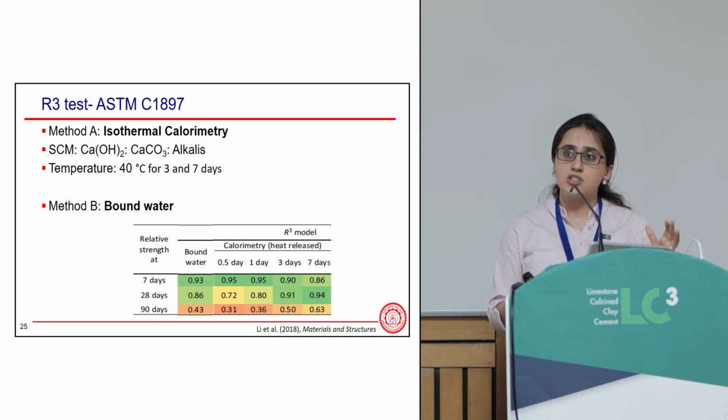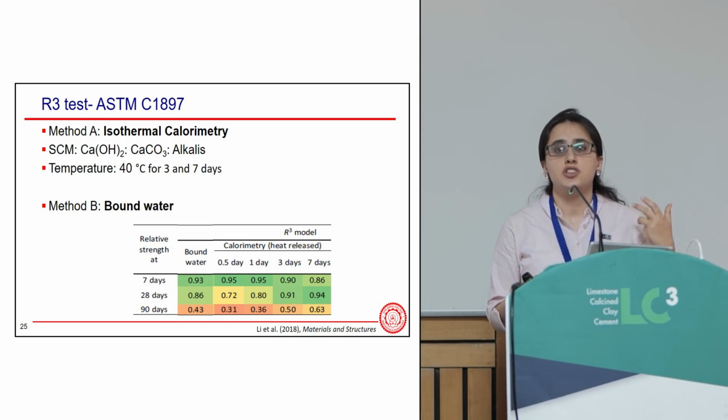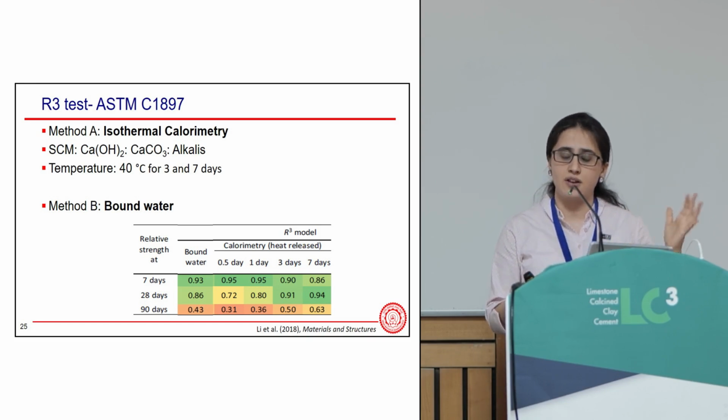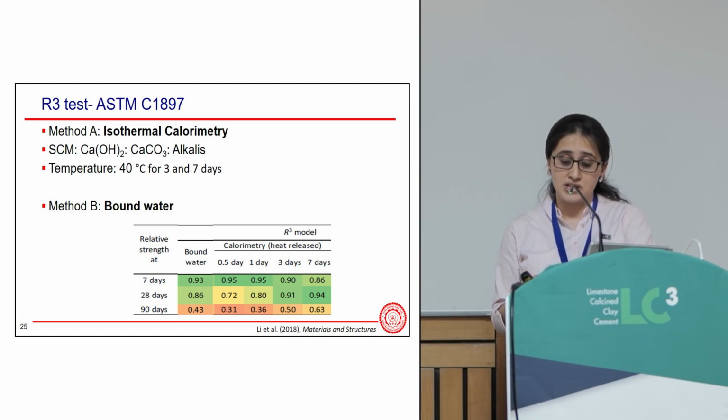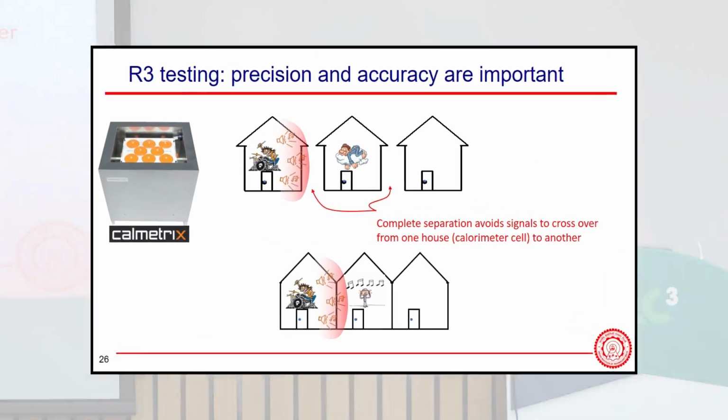There have been a lot of studies done on the R3 test using different types of SCMs and different types of clays, and they have found that there is a good correlation of the R3 test with the 7 and 28 days compressive strength results.